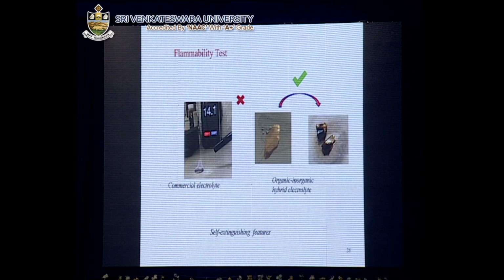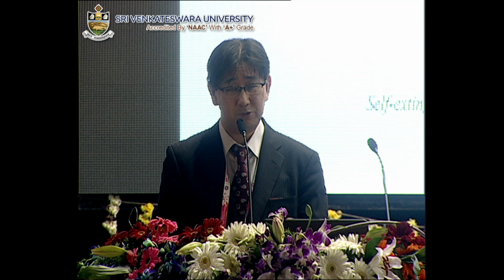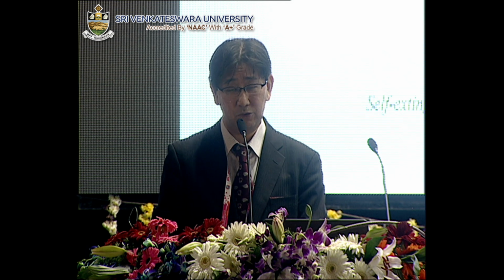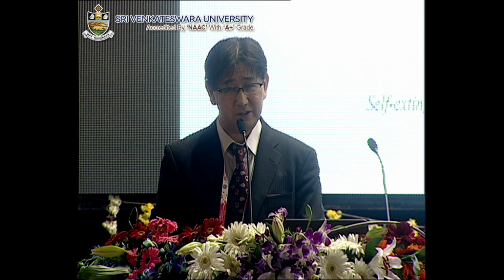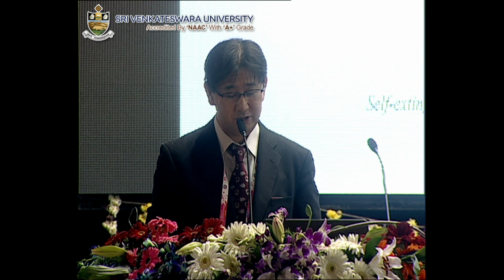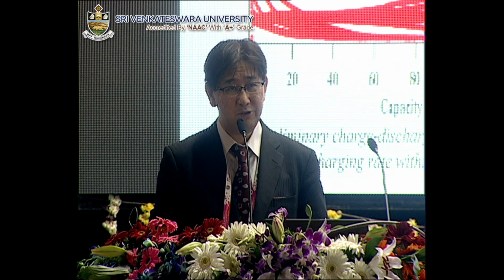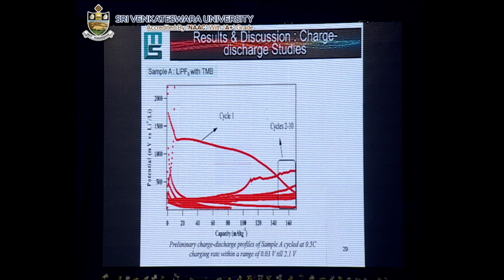And next, the flammability test was also carried out. When commercial electrolyte was exposed to fire, it immediately caught fire. However, when our material was exposed to fire, even after 1 minute of treatment, it did not catch fire at all, and only color changes were observed, showing self-extinguishing features. And by using such a non-flammable solid electrolyte, we tried to fabricate a lithium-ion battery.